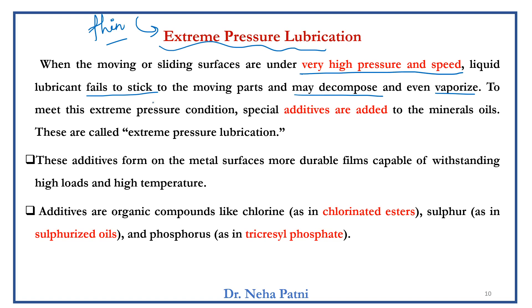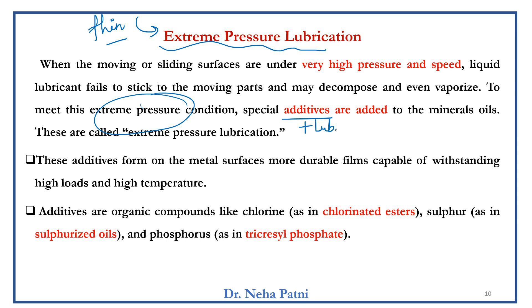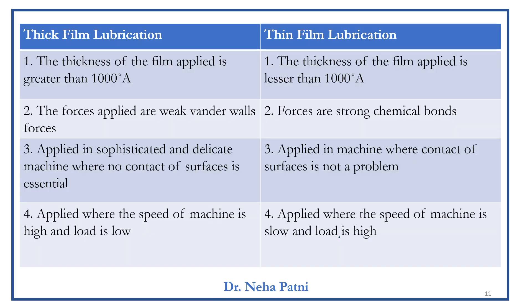In extreme pressure conditions, you have to add special additives. These additives react with the lubricant and change into a derivative that is strong enough to sustain that much pressure. The additives help make the lubricant more durable and strong, capable of withstanding high load and temperature. Normally chlorine, sulfur, and phosphorus are used as additives — they react with the oil, forming a derivative that is comparatively more stable than the original lubricant.